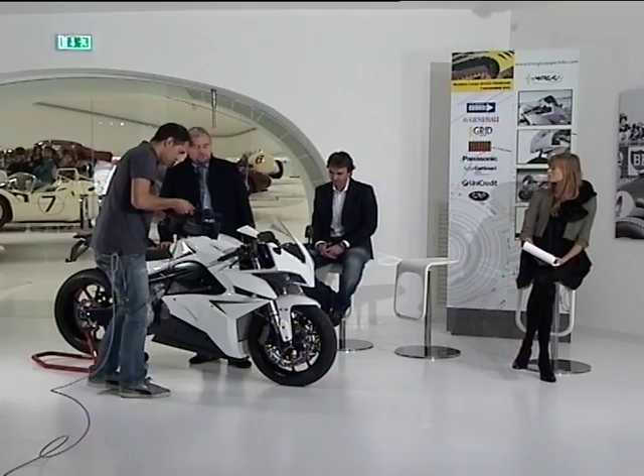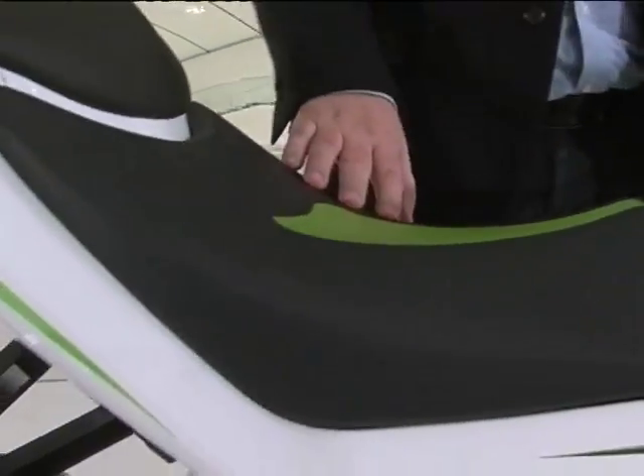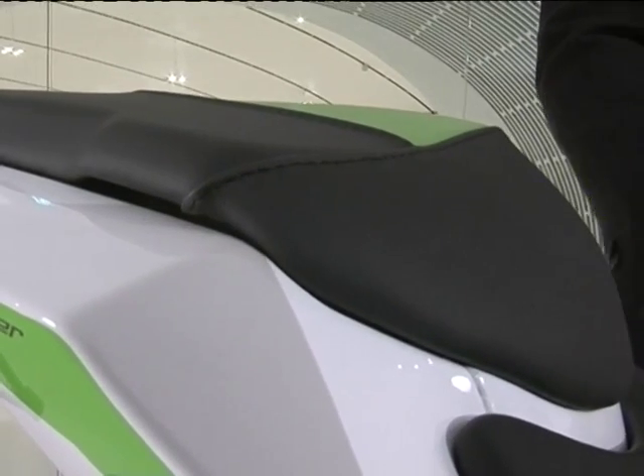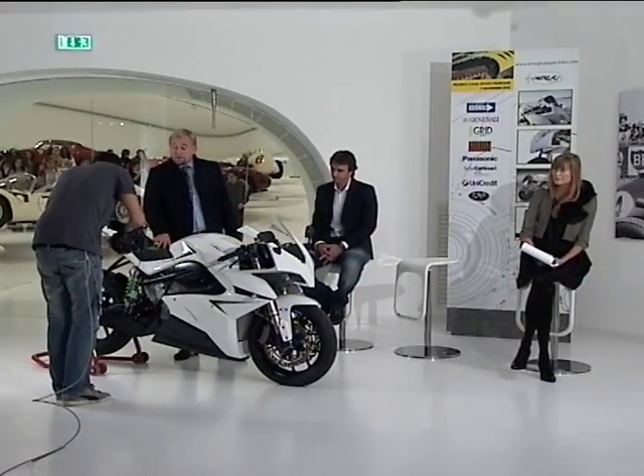Then we also used another high-performing material, Windform SP, which is again filled with carbon fiber. We used this material for the two plate seats, which are high-loaded parts that have to withstand vibration and bumps. With this material we have improved toughness and impact resistance.